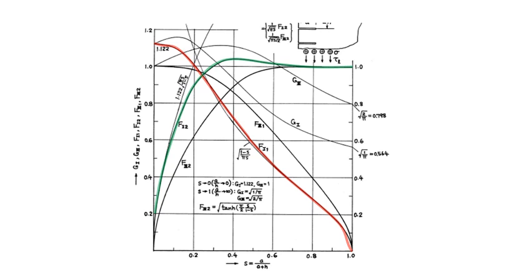And what's interesting there is you start off in the lower left portion of the plot. The stress intensity factor compliance factor actually goes up, and it peaks right around S of 0.4. And after it peaks at that point, it actually goes down a little bit, which is a very strange thing to think about. Now, when you look at the stress intensity factor of the green line, you can consider that the h value is not changing. Your cracks are not getting closer or farther apart from each other. They're maintaining a constant, and therefore that green line actually represents what the classic stress intensity factor would be doing as the crack grows.